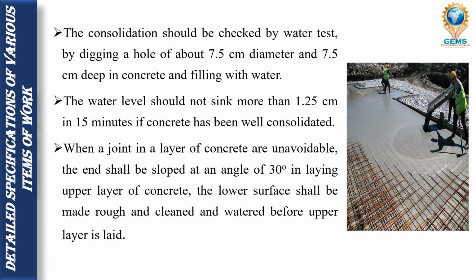Then the next one is what? The consolidation should be checked by water test. The water level should not sink more than 1.25 centimeter in 15 minutes. So through this test and its result only we can know whether we have done the laying and compaction correctly or not. Okay.